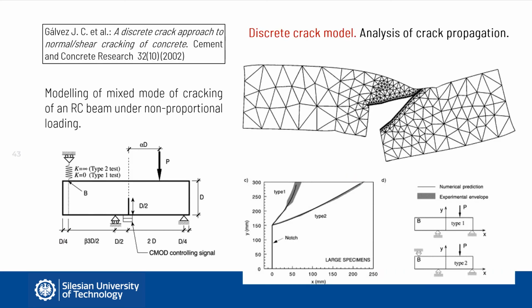I would like to close up this lecture by presentation of two examples of application of crack models. The first one is related to the use of a discrete crack model to follow the propagation of a crack in an atypical notched beam and verify the model against the experiment. We can see here how a discrete crack is being formed by introduction of discontinuity of the mesh, which requires remeshing in the close vicinity of the crack path. This is a good example of application of a discrete model in an element with one dominant crack of predefined location. It is known that the crack will initiate at the tip of the notch, and the analysis will progress from this node.